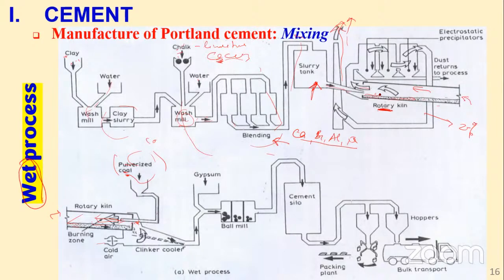The temperatures along the kiln are different. Where the hot air is starting, towards the bottom or the end of the kiln, the temperatures are very high. But as the air is escaping on this side, the temperatures are not very high. So as the slurry flows, what starts off here contains water and all these mixtures. So moisture evaporates when the temperatures are around 100 degrees centigrade. If you subdivide your kiln into parts, the uppermost part is where we lose moisture.